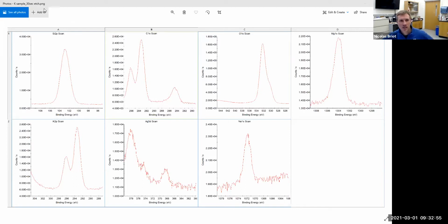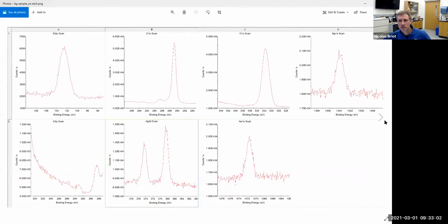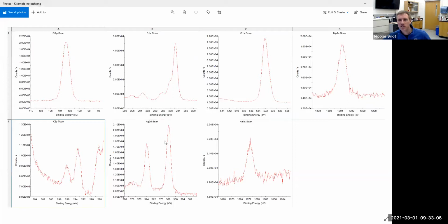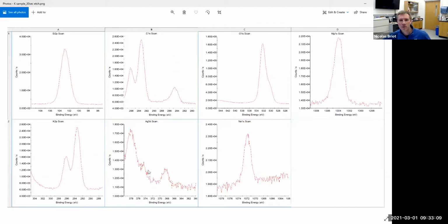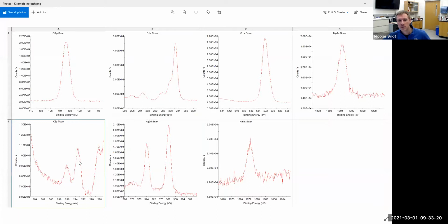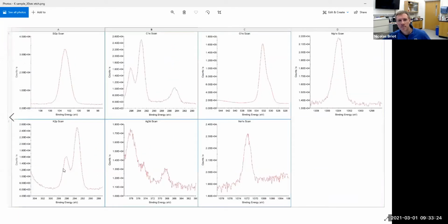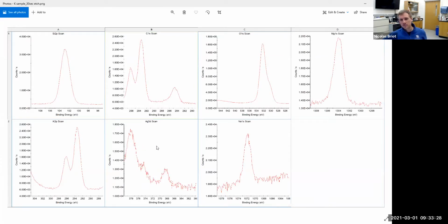So what you can see here, after I clean the surface a little bit, is that the silver peaks are mostly gone. That's the silver that we had before, that we don't really know how it got here. After cleaning, those two large peaks are pretty much gone. So that tells me that the silver was maybe just some residue at the surface. But the potassium signal, which was there but a little faint, we now clearly see very nicely. So that would tend to indicate that there was some silver residue at the surface. I'm not sure if it was cross-contamination when rinsing things, but it goes away as soon as you get a few tenths of nanometers below the surface, and then you are clearly into the potassium signal. Okay.